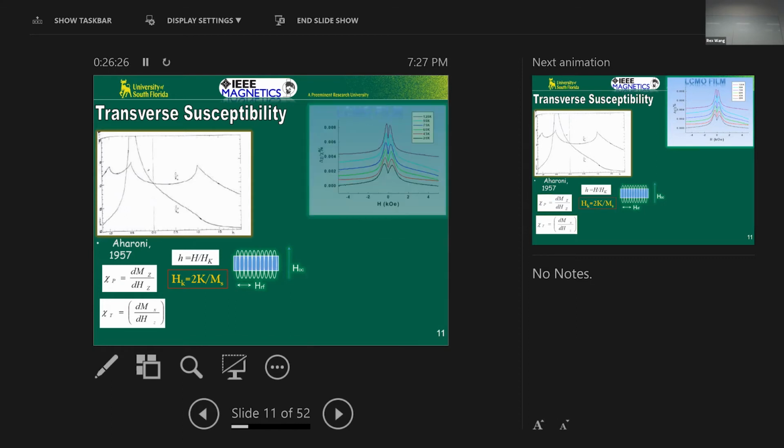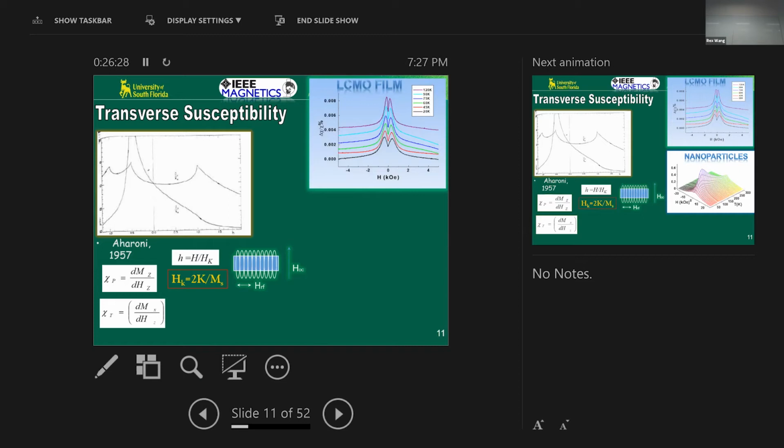We've been seeing these peaks for more than 15 years now. We can measure the anisotropy field in any kind of magnetic material, whether it's a thin film, a single crystal, bulk, nanoparticles, you name it, with a high degree of sensitivity. That's what gives us this precision for looking at effective anisotropy. So these are from manganite films. They are a class of complex oxides and well studied. The peaks are sharp because these are thin films and the magnetization directions are well defined.